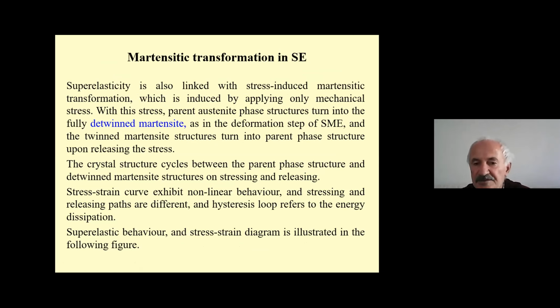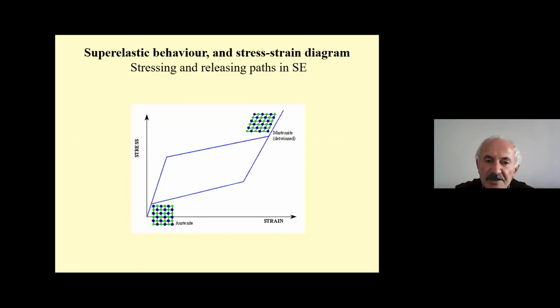Superelasticity is also linked with stress-induced martensitic transformation, which is induced by applying mechanical stresses. With this stress, the parent austenite phase structure turns into the detwinned martensitic structure, as in the deformation step of the shape memory effect, and the detwinned martensitic structure turns into the parent phase structure upon releasing. The crystal structures cycle between parent phase structures and detwinned martensitic structures on stressing and releasing. It is important that the stress-strain curve exhibits nonlinear behavior, and stressing and releasing paths are different, and the hysteresis loop refers to the energy dissipation.